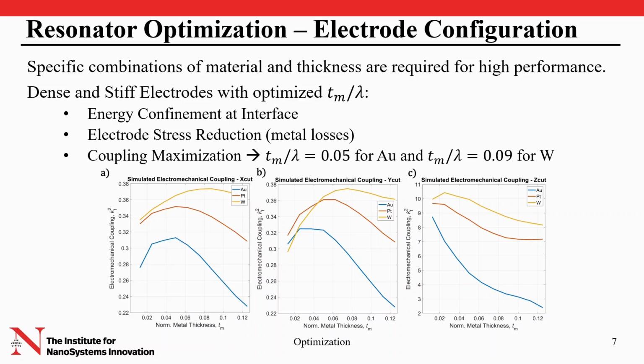To leverage leaky SAW, we need dense and stiff electrodes with an optimized ratio between the thickness of the metal and the wavelength of the resonator. This is so to confine the energy at the interface while reducing the stress in the electrode, which is a known cause for metal losses that ultimately impact the quality factor. Using COMSOL simulations, we derive the dispersion curves for the coupling factor for X, Y, and Z cut. And we can see that for both gold, platinum, and tungsten, we can find a maximum that maximizes the electromechanical coupling.